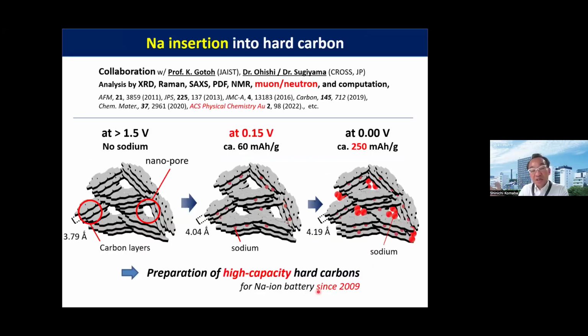So after sodiation of hard carbon through electrochemical reaction, we carried out many different strong analytical tools like X-ray and small angle diffraction, NMR, muon, neutron, computation, and so on. And our conclusion is, first, in the higher potential region, higher than 0.15 V, the sodium can intercalate into the stacked graphene layers, carbon layers.